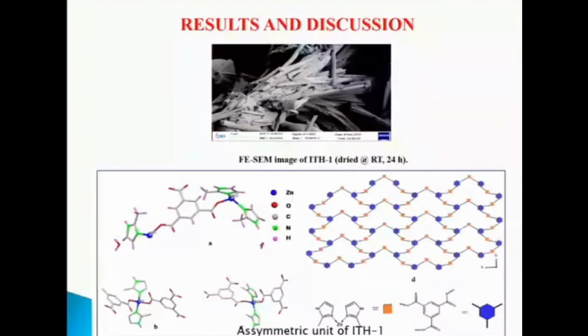The first picture represents the FE-SEM image of ITH1. Pillared crystal formation was obtained with average sizes of rods of 2 to 3 millimeter length and 1 to 1.5 millimeter width. From the single crystal XRD, it is observed that ITH1 is made up of infinite sheets of zinc 2+ ions connected via BTC3- anion with 2-methyl imidazole units. The asymmetric unit of ITH1 consists of two crystallographically distinct zinc 2+ ions. Both of the zinc 2+ ions have distorted tetrahedral geometry, coordinating with the carboxylate atoms of 2 BTC and the tertiary nitrogen atoms of 2 different 2-methyl imidazole units.